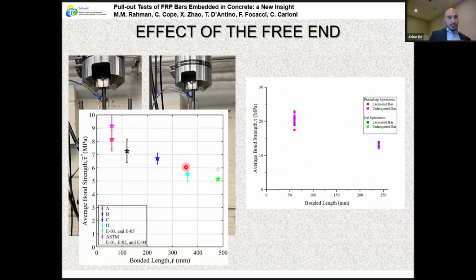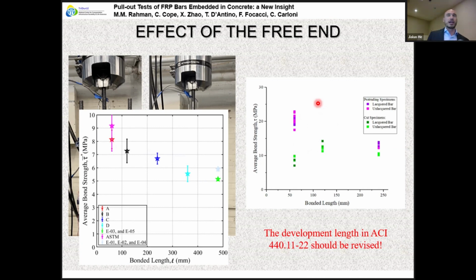But if you test the same specimen without the protruding part, without that little appendix at the end, this is what you see. These are the green ones. So in other words, for the first length, the 5 diameters, having or not having a protruding part at the end of the specimen makes a large difference in the peak load or in the average tau, which means that this is an important factor. When you go into the field, the manufacturers go to the DOT and tell them, oh, this is my tau based on ASTM, but which one is the tau? How do I compare this material with another if the majority of the tau depends on the protruding part? And this protruding part has a different effect if the bar is different.